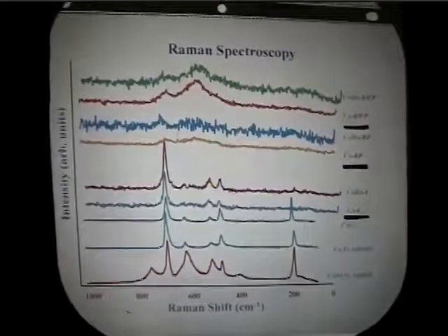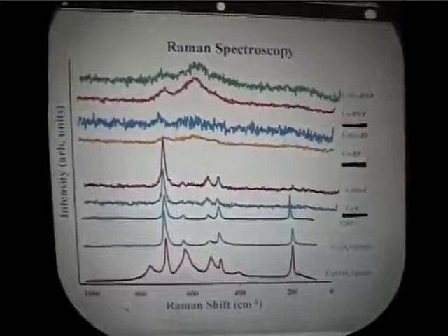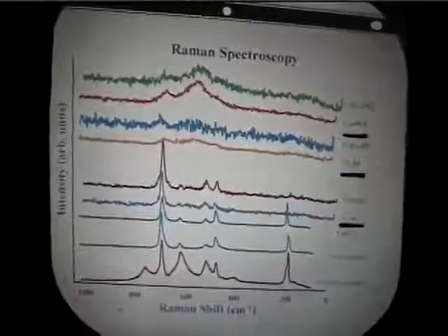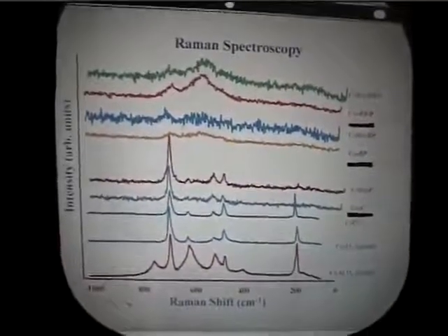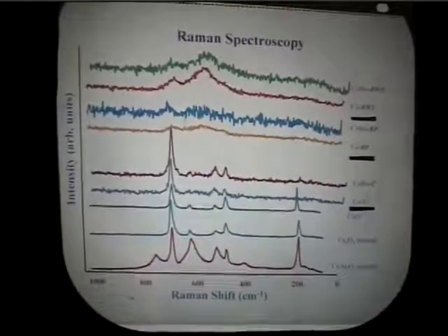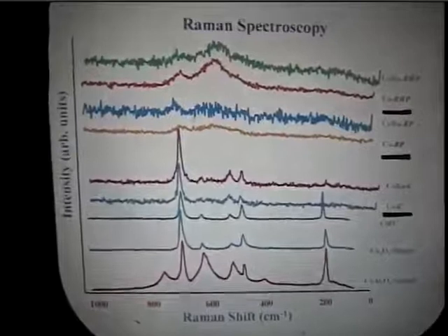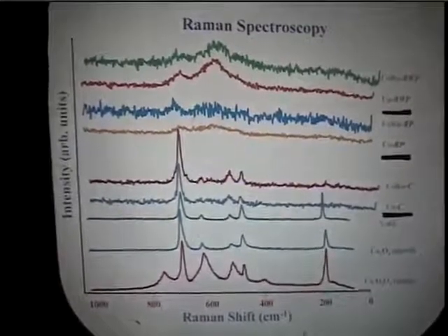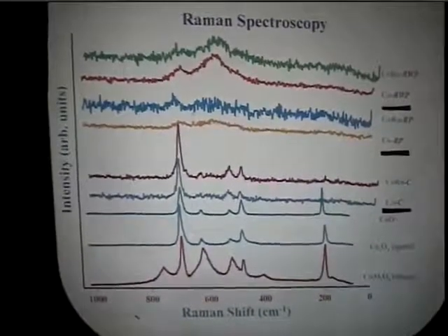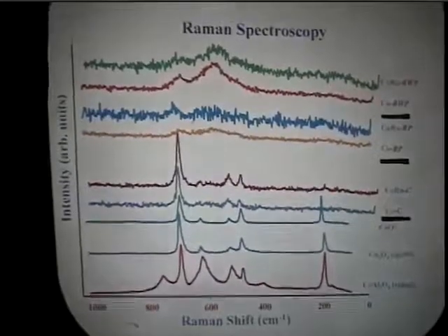So these Raman bands can be assigned to the cobalt aluminate formation, which occurs probably due to cobalt ion migration into the alumina matrix and from surface non-stoichiometric cobalt aluminate formation.